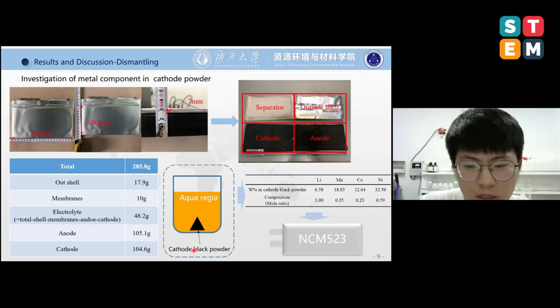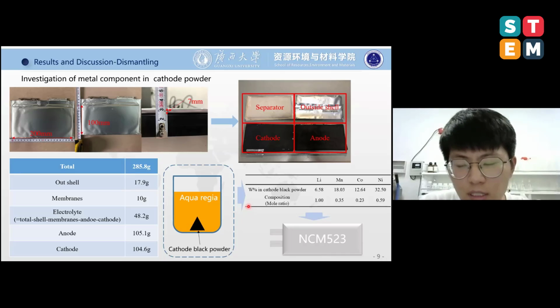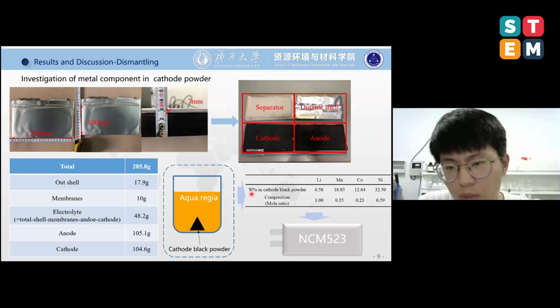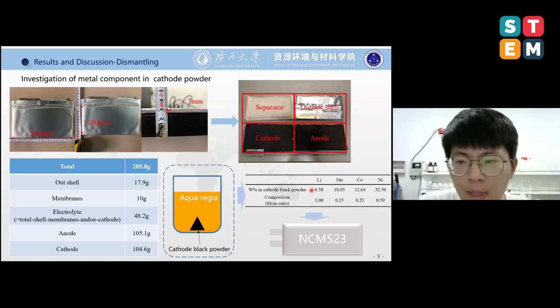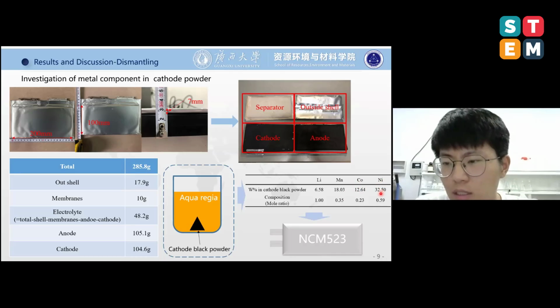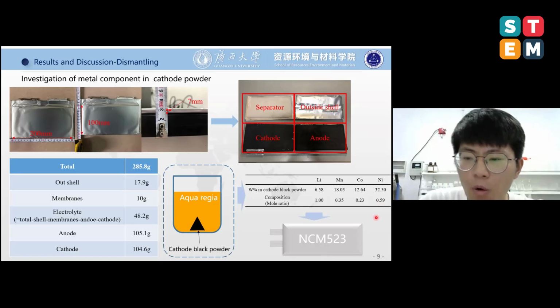And I want to know what is contained in the cathode black powder. So we put the cathode black powder into aqua regia to dissolve it, and use ICP to measure the concentration. After calculation, we get the weight percent in cathode black powder. Lithium is about 6.58%. Manganese is 18.03%. Cobalt is about 12%. Nickel is about 32.5%. And for the composition inside, lithium is 1, manganese is 0.35, cobalt is about 0.23, nickel is 0.59.